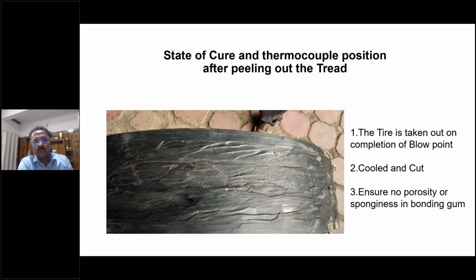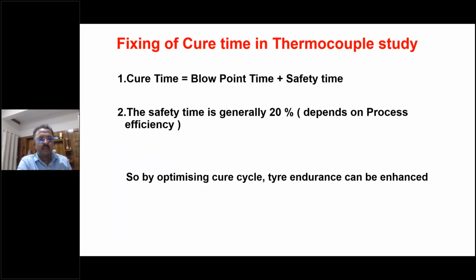And after curing, just peel up the tread. See the bonding, whether the bonding is good or not. No porosity, no sponginess. And normally the cure time is set as the blow point time plus safety time. Normally, 20% is given as safety. Suppose the blow point time in the curing chamber is 1 hour. You put 1.2 hours.